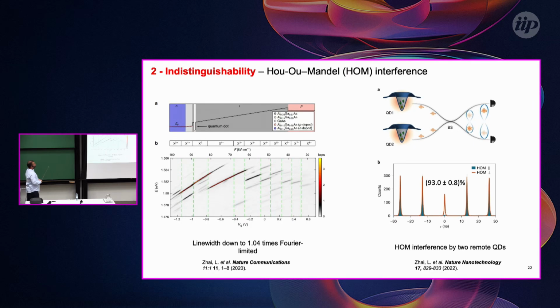Okay, the second characteristic that we look at is the indistinguishability of these quantum dots. In 2020, the group of Richard Warburton, from Basel in Switzerland, took one of these gallium arsenide quantum dots and embedded it inside a PIN device. With this, they managed to control the charge environment around the quantum dot, and they showed that they can get a linewidth almost at the resolution limit. With two samples in two different cryostats, they did a two-photon interference visibility measurement, and they demonstrated that they can reach values around 93%, which is really good. This kind of sample was also a first test, and there is a lot of room for improvement to get better values. Basically, what indistinguishability gives us is how similar one photon looks to the other. If it's 100%, this means that all the optical characteristics are the same.